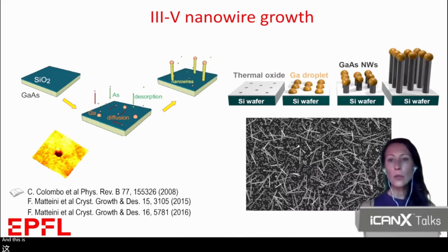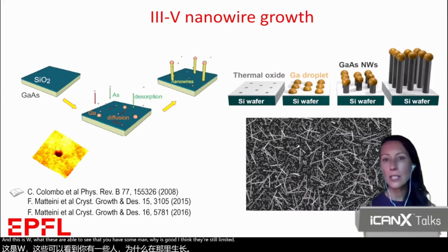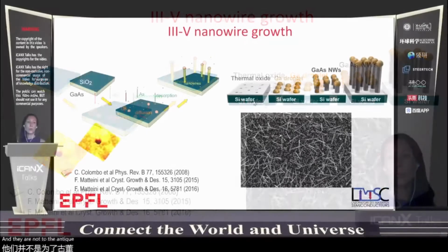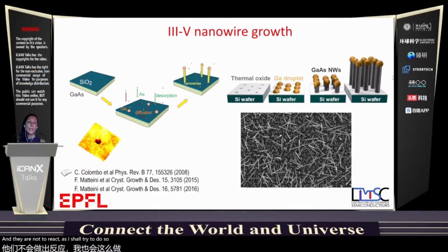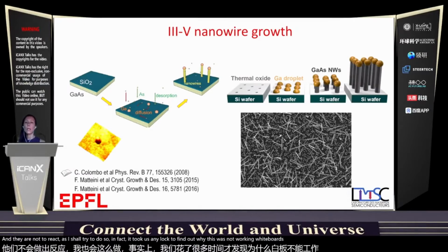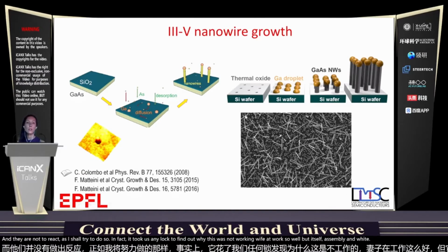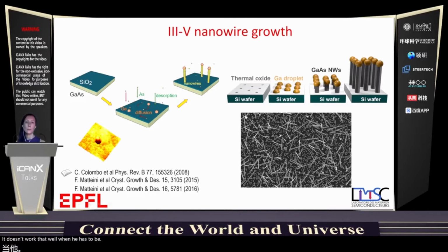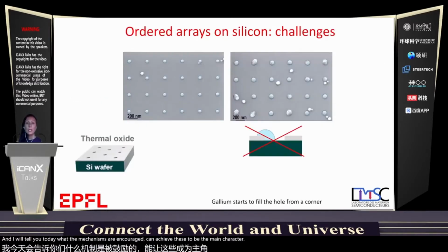And this is a top view of this array, in which you see that you have some nanowires growing. There are filamentary crystals that are here. You have a lot of stuff in between, and they are not oriented as I showed in this image. So in fact, it took us very long to find out why this was not working, why it works so well when it's self-assembly, and why it doesn't work that well when it has to be ordered. And I will tell you today what the mechanisms are and how you can achieve this with a very high yield. So we started looking at the initial stages because it seems that this is the moment in which things start to go wrong.